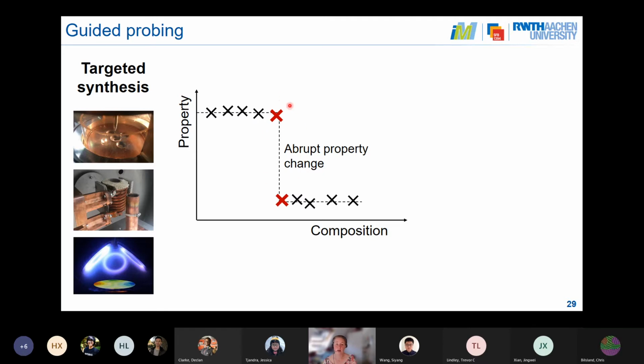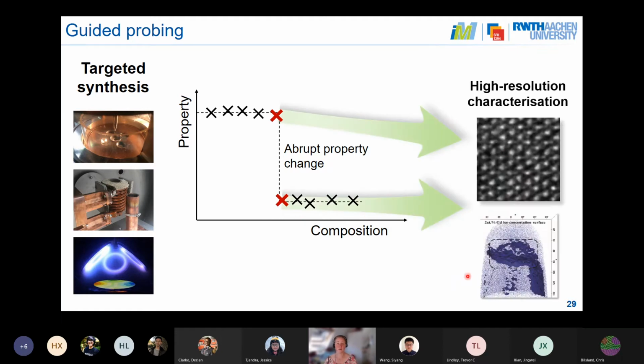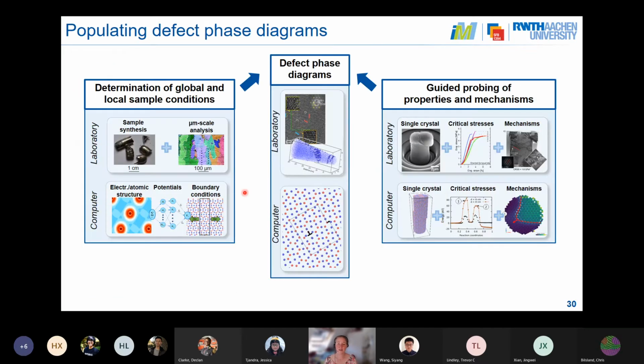And this is then where we use high resolution methods to do characterization, for example, TEM or atom probe tomography, and where we can also go to different synthesis methods, like, for example, starting with thin film combinatorics and going to targeted synthesis of individual bulk phases with a very, very tightly controlled composition rate. So what we do then is we'll have these defect phase diagrams where we know everything about the defects from high resolution experiments and simulations, and we'll have to connect them with global and local sample conditions, like, for example, the chemical potential around a defect, but not for the whole sample, but you will actually be able to look at this a few microns around it.